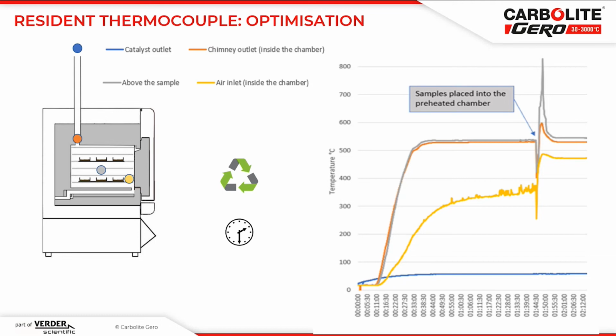Often the furnaces are preheated for these type of tests. And then you can see the spike that follows, and specifically the spike where the grey thermocouple is sitting, so above the sample. And this is showing the exothermic reaction of the sample. So the sample's taking the localized temperature up to 800 degrees over the sample. The reason this is important is if we can measure this and we can prove this, then we can also potentially reduce the operation time, so the residency time in the furnace.